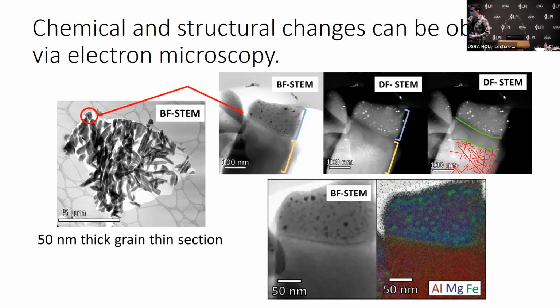Just below this, we have an energy dispersive X-ray spectroscopic chemical map. We have a magnesium-rich melt splash on top with the embedded nanophase iron particles, and just below that, we have aluminum, indicative of our lunar anorthite. For the remainder of this talk, I'm just going to focus on the solar wind damaged rims and the solar energetic particle tracks.